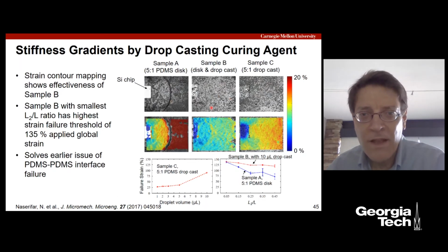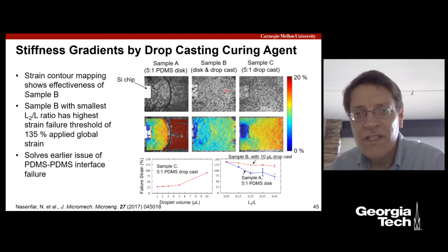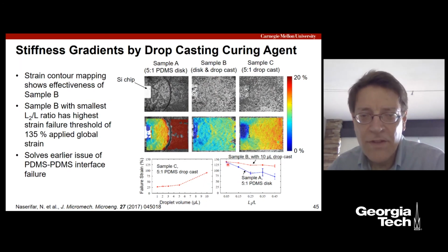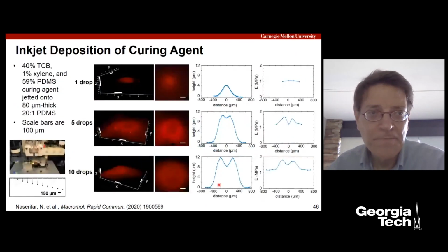And when we did those pull tests, we found, with some contour mapping using carbon black on top, you can see the center has the 5-to-1 disk and the drop cast, and you can see a nice smooth transition of strain. And indeed, it's that sample that gets the highest failure strain percentage, in this case around 135% before we started to see delamination anywhere in the system.